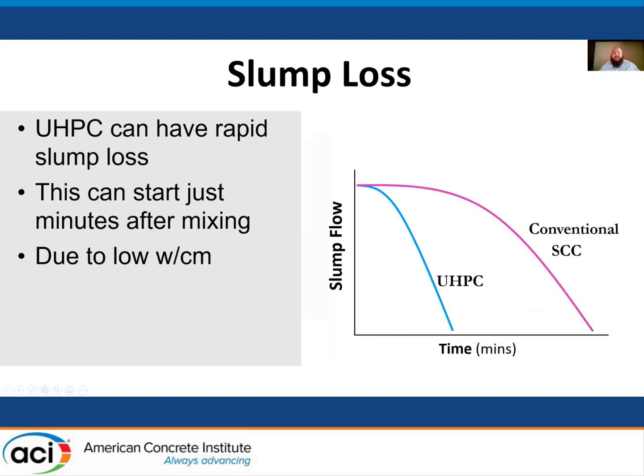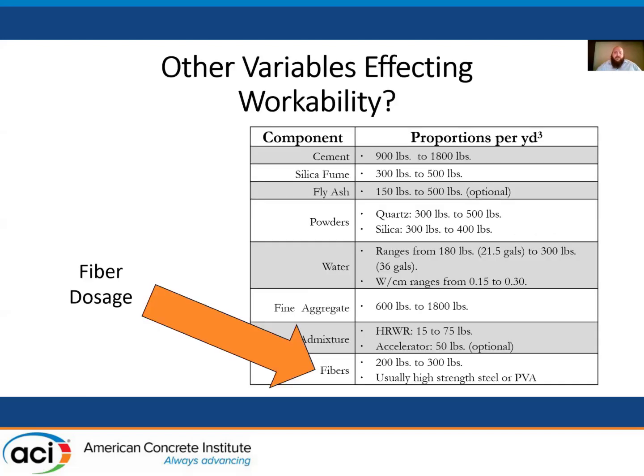Same thing with slump loss. Like I said, you may start out with a really good flow right when it gets out of the mixer, and then over a little bit of time, with the UHPC, the workability just starts going down quickly. You can compare that to a conventional SCC where you really want to extend that workability a lot longer. And a lot of times you can get there, but when you have these lower water cement ratios, if there's not as much reaction with the water reducer over time, it's not as effective either. And if you lose water through evaporation and other things, just be aware of that.